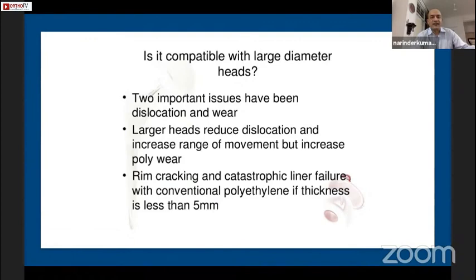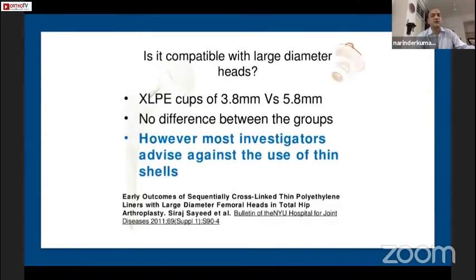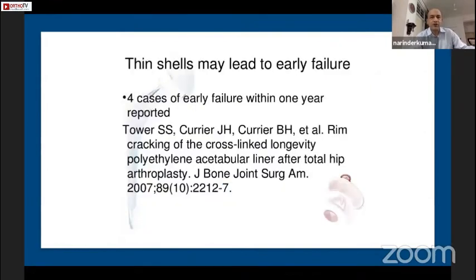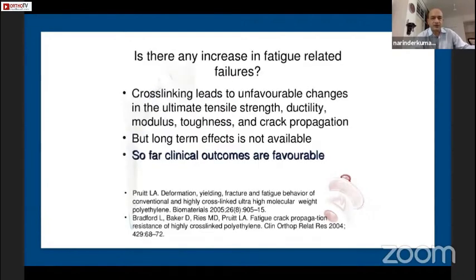So, with fatigue setting in at a longer time, rim cracking and liner failure can happen with conventional poly as well as with cross-link poly if thickness is less than 5 mm. Although there is a study which compared a 3.8 mm cross-link poly with that of 5.8 mm and found no difference. But most investigators, most surgeons would not like to use a thin liner less than 5 mm, definitely, because they are going to lead to early failure. There are cases which have been reported.